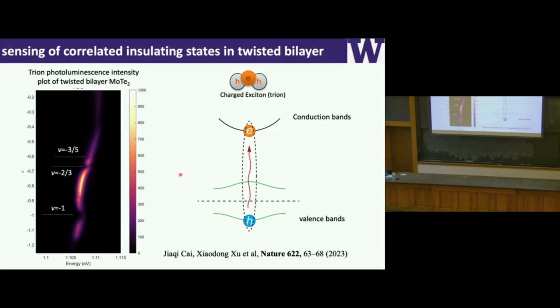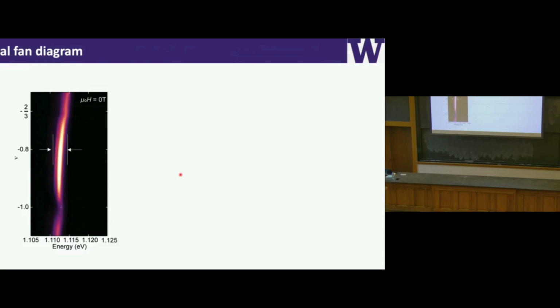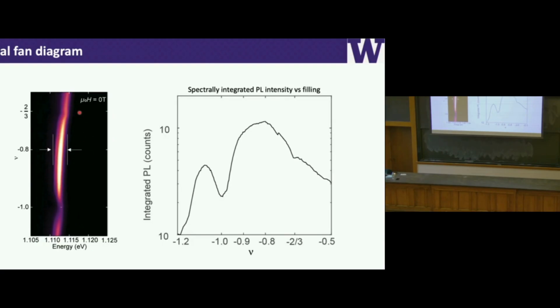So what we can do experimentally is a spectral integration of photoluminescence intensity. For example, I can do integration over these spectral windows, then I plot the intensity as a function of filling number again at a particular magnetic field. And I can identify these dips, which correspond to these integer or fractional states.